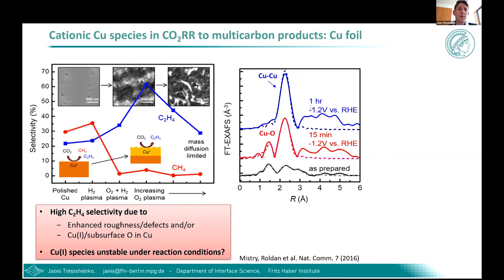But one needs to keep in mind here that this particular sample maybe is not the most convenient system for X-ray absorption studies. The reason for that is that XAS, similarly to other spectroscopy methods, is a sample averaging technique, which means that the information which we are collecting is averaged over all species in our sample. And if our sample is a bulk-like material, as in this case, there is still a possibility that some fraction of oxide species exists near the surface. We just don't see it in our sample average data.